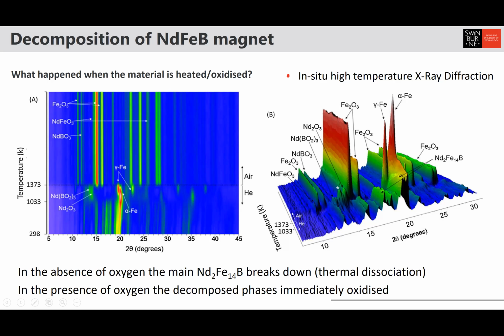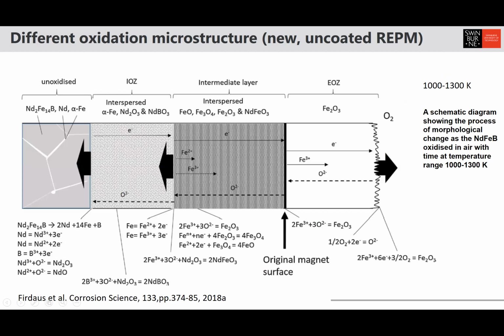So we did quite a systematic study on this one. We oxidized new uncoated REPM, and we found that if we oxidize it at different temperatures, it will give us different types of microstructure. So don't worry about this complex schematic, but in essence, when you oxidize it, let's say here from 1000 to 1300, you will form quite a thick layer of Fe2O3 on the surface. We call that the EOZ here, external oxidation zone, mainly consisting of Fe2O3. And then we have an intermediate layer where we have interspersed FeO, Fe2O3, Fe3O4, and NdFeO3. We have the IOZ, where we have iron as well.